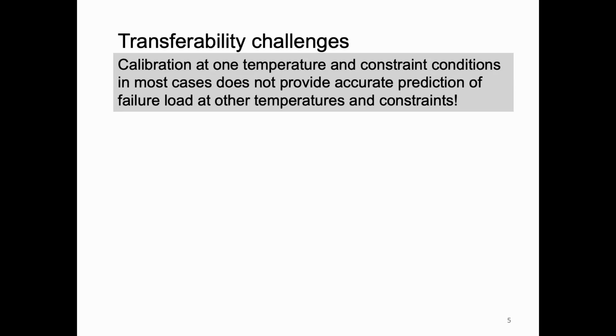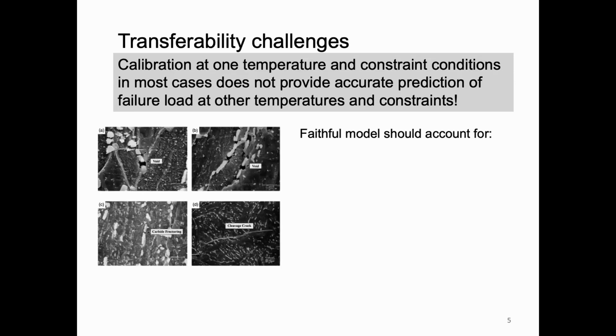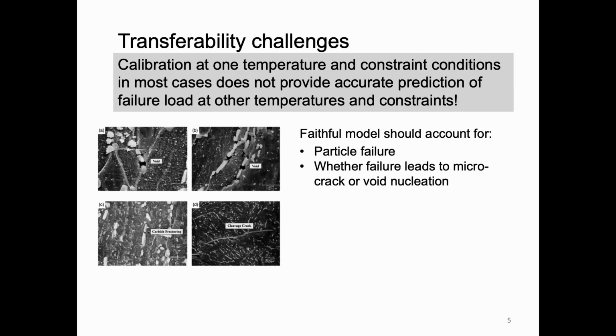In a way, if you know how the deformation properties change, you would like to be able to put it in the model and predict how the fracture toughness properties would change. But that's exactly what is not possible. And what we want to develop is a faithful model that can capture the particle failure, and it should be able to decide whether this failure leads to microcrack formation or a void formation.